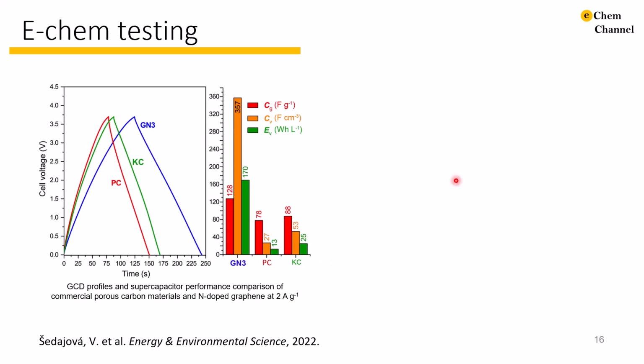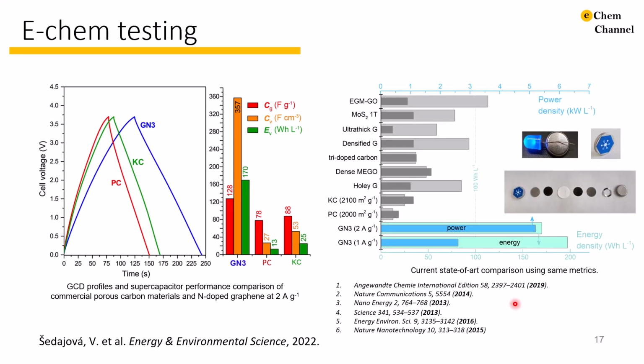The energy density is the Achilles heel of supercapacitors, whereas the high power densities are one of their greatest strengths. The GN3 cell demonstrated groundbreaking performance by delivering both ultra-high energy and power density. And to set these results into the context of the current state of the art, they are presented alongside the best literature data on top-performing materials.